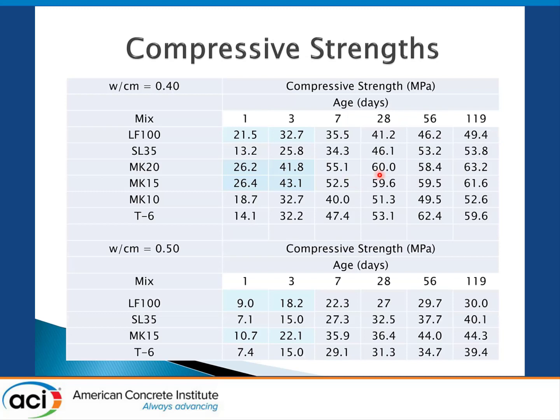The strength development was good. What you see here is the early strengths of the 15 and 20% metakaolins at 1 day and 3 days exceed that of the Portland cement control mixture by almost 1,000 psi, or 7 megapascals. Then the strengths continue to rise over the time frame up to about 4 months in this case. The ternary mix was slower at early age, but again, that was probably due to the higher dose of admixtures and higher air content, but they did catch up at later ages.